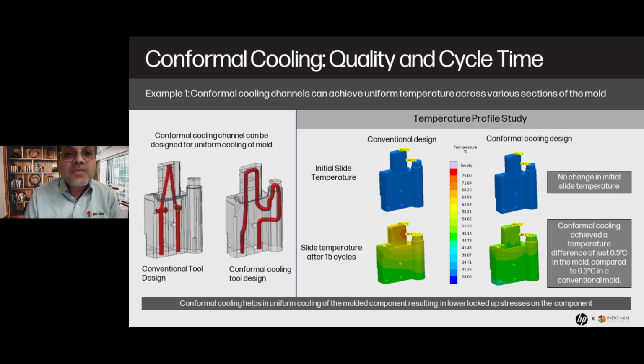Now, starting with the conformal cooling, how it really helped us to maintain the uniform temperature across the mold element, which helps both in cooling the component uniformly and at the same time heating the mold, so that the material does not freeze unduly at certain areas. If you look at the tool element in the picture here, the conventional tool design allowed us only a straight line. That means the cooling was very inefficient. Because we adopted 3D printing, the conformal cooling tool design allowed us to take the cooling channel as close as possible to the molding surface.